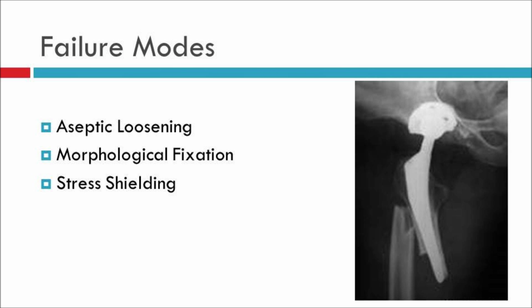There are generally three modes of failure that are associated with load-bearing implants. The first, aseptic loosening, occurs when material begins to wear, causing particulate matter to be released into the surrounding environment. This can cause surrounding tissue to die and result in implant loosening. And this has actually been kind of a big problem recently with a lot of implants that are using ultra-high molecular weight polyethylene.